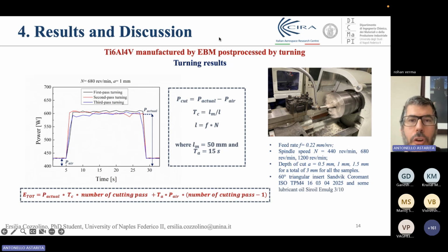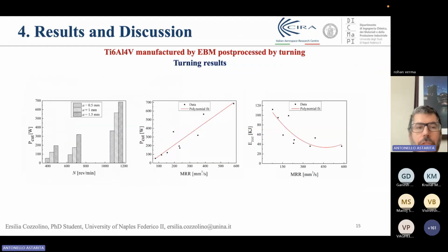Okay. Again, we performed machining operation under different conditions. You can see that the spindle speed varied from 440 revolutions per minute to 1200 revolutions per minute. We also varied the depth of cut, and we used Sandvik Coromant tools with an industrial lubricant. So we used state-of-the-art tools with the lubricant most used in industrial environments, at least in Italy. And we carried out a full experimental campaign by varying the cutting process parameters, trying to develop this equation that allows you to calculate the total energy required to perform a machining operation.